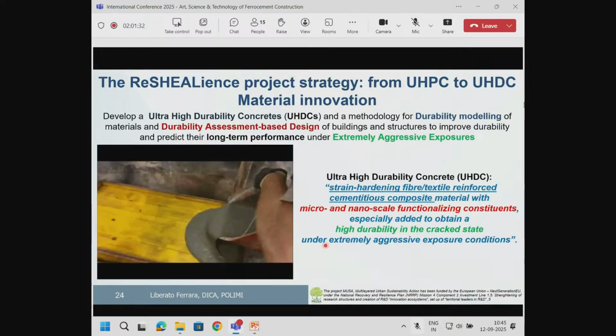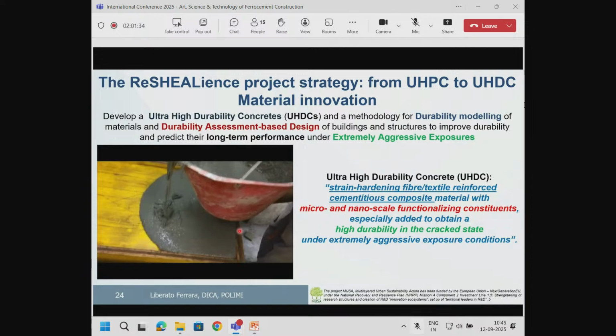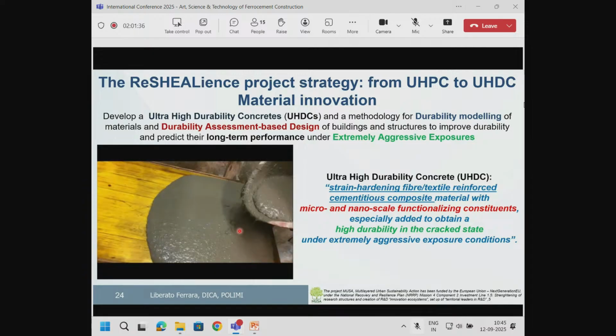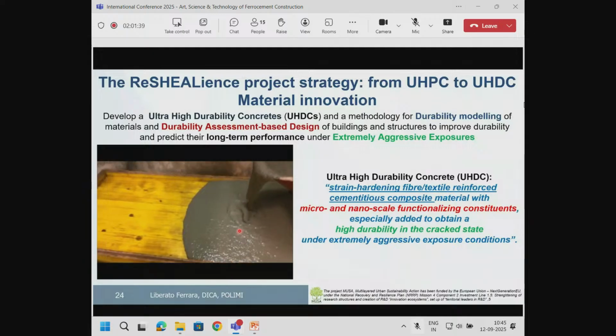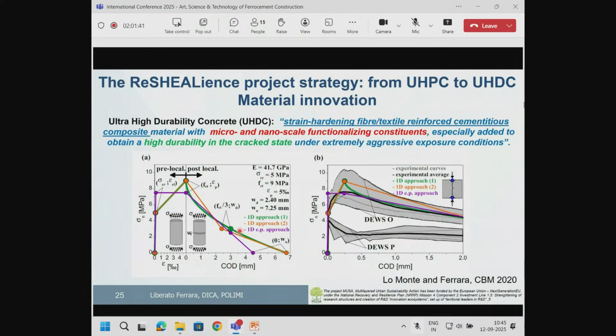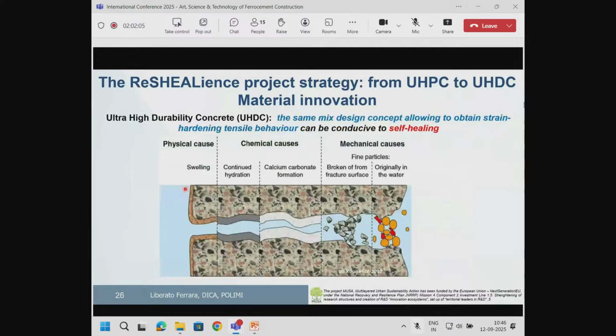So we started from UHPC materials, ultra-highly durable concrete, and we wanted to scale this concept not only to the compressive strength, but we wanted, and this is the lesson that we also learned from ferrocement, this material which in tension is able to withstand not only high stress levels, but also to deform up to considerable levels. You can see here 0.5%, which is far beyond the yielding strain of conventional steel.